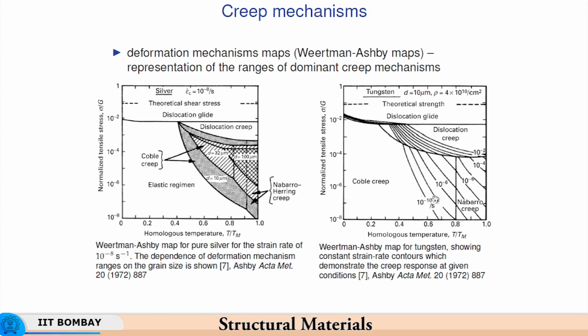So, this is Coble creep, and this is basically diffusion around the grain boundaries. So, Coble creep would be proportional to the cubic power, that is d cube, and so it is much more sensitive to grain size as compared to Nabarro-Herring creep. Nabarro-Herring creep is sensitive to the square power. So, that is the difference it makes.